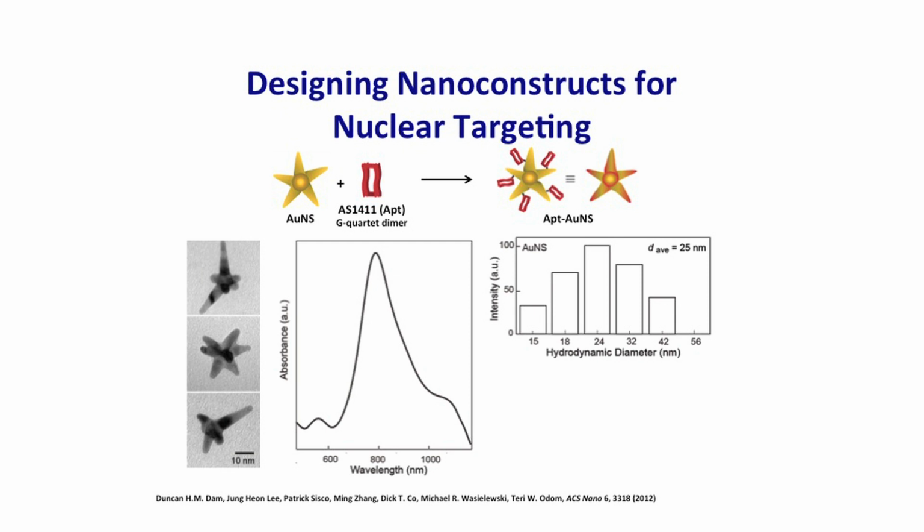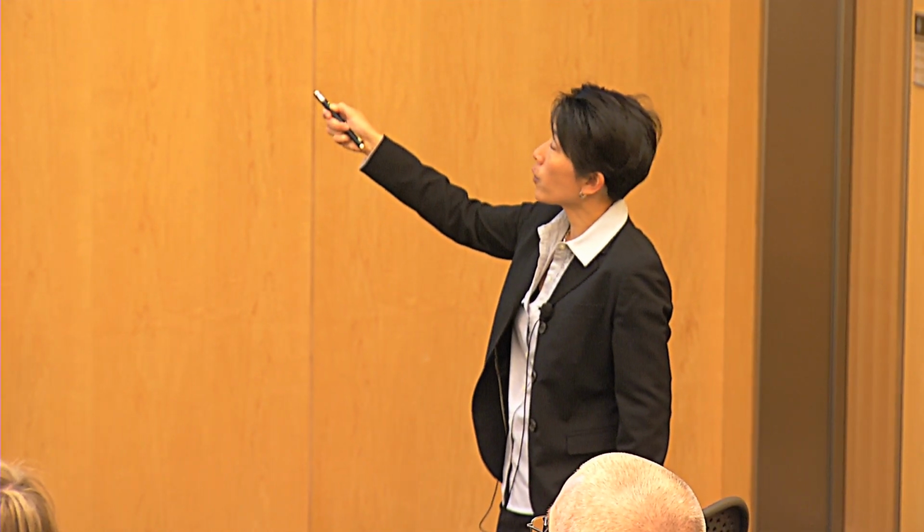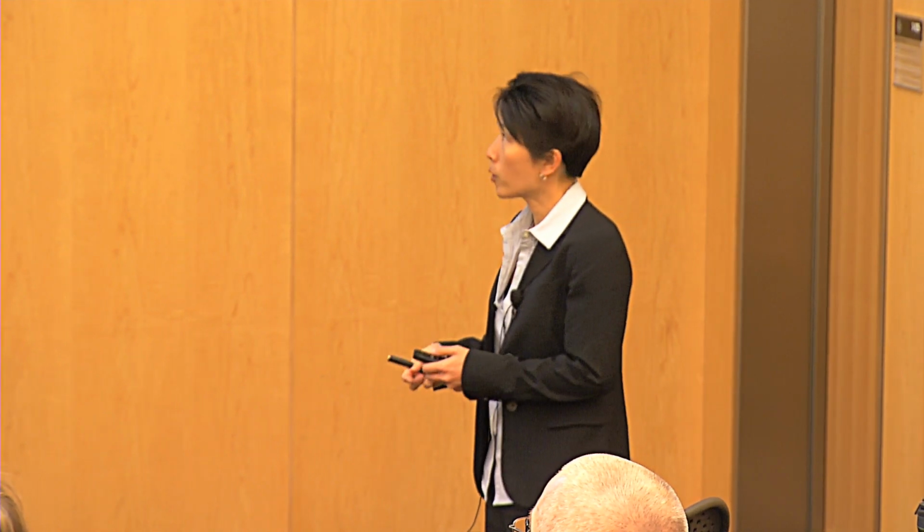What we then want to do is put the aptamer onto the surface. Part of the reason why all of us here at Northwestern like gold is because gold is very easy to functionalize through a thiolate bond. You can put a thiol onto any type of DNA or siRNA, and under the appropriate reaction conditions, you can just form a chemical bond. Once you form a chemical bond, this type of entity is extremely stable. We also do dynamic light scattering to make sure that we have the relative increase that we would expect if we actually did attach the drug molecules to the surface.